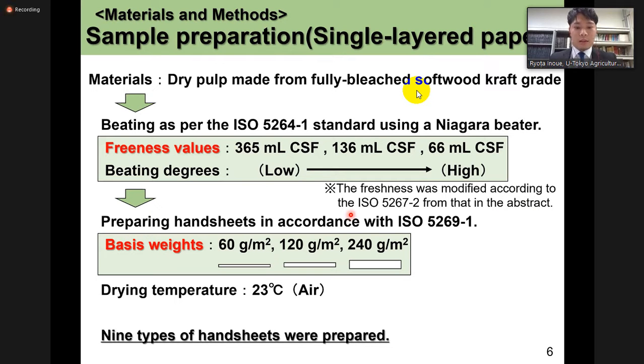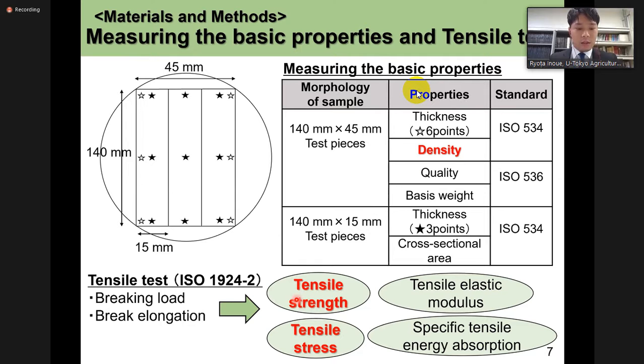We prepared 9 handsheets from the 3 pulp samples at target base weights of 60, 120, and 240 grams per square meter. The handsheets were air dried at 23 degrees. We prepared these 9 types of handsheets. Here, I'd like to explain about measuring the basic properties and the tensile test. First, we cut the handsheet into 140 millimeters by 45 millimeters test pieces. We measured thickness and quality, and then calculated the apparent density and base weight.